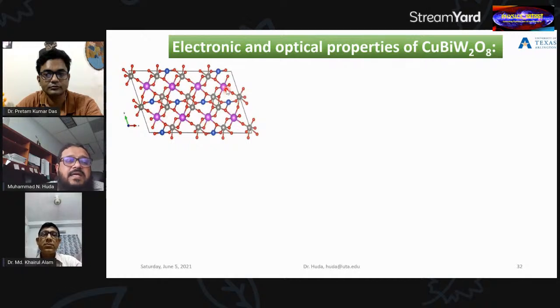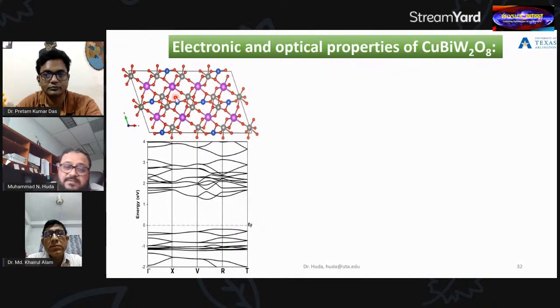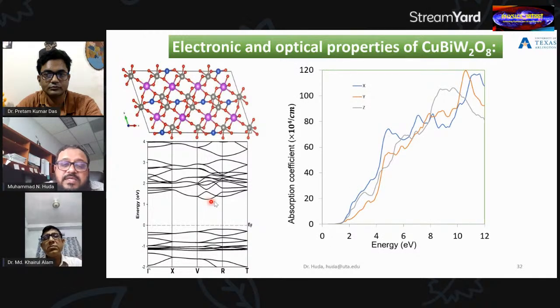This is a mineral type grouped as the scheelite structure, a rather distorted scheelite structure. This is what we decided upon, that should be the ground state energy crystal structure for copper bismuth tungsten oxide. Once we decided on the structure, we calculated the band structure. This is the valence band. These are the conduction bands, the unoccupied bands, and the gap occurs here. Compared to tungsten oxide, this gap is smaller. But then the question is, what about the optical absorption? Because that is what we are targeting from the beginning. This is the optical absorption we calculated.